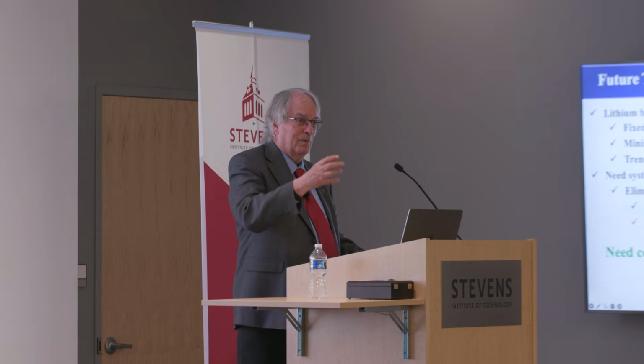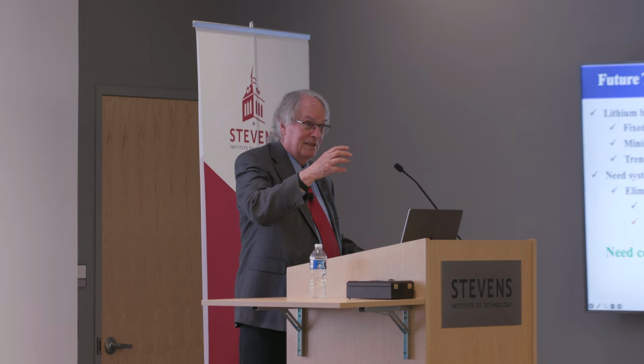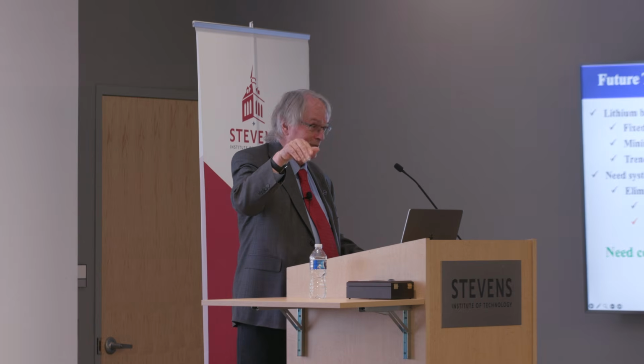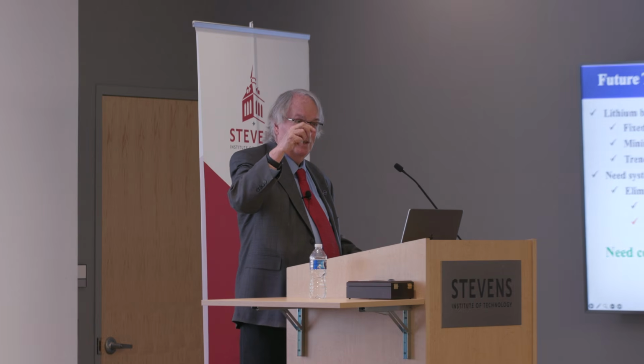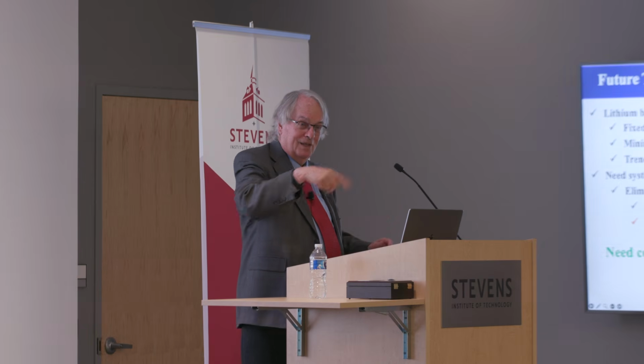All right, so we are not looking to build bigger crystals. We are looking to build smaller but more stable crystals. We want crystals about 3 microns in size, not too small, but if we get bigger than that, those crystals will crack. And we studied this at length at Exxon when we had these large crystals. We could actually look at them under an optical microscope as we put lithium in and see the cracks forming. Thank you.